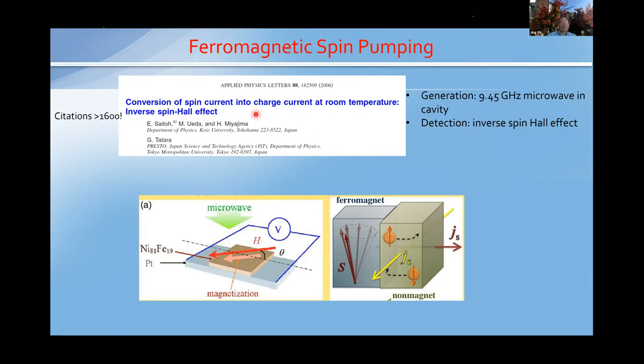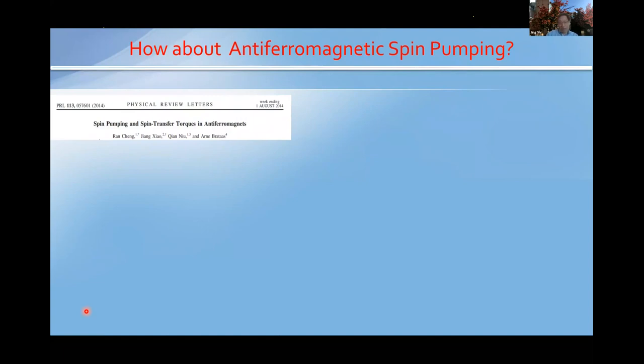So this original paper used 9.45 gigahertz to excite ferromagnetic precession. The resonance peak in nickel iron or any other materials can be easily achieved with the microwave. But how about the antiferromagnet spin pumping? The inherent difficulty is this high energy, the high magnon frequency or energy. However, theoretically it was proposed in 2014.